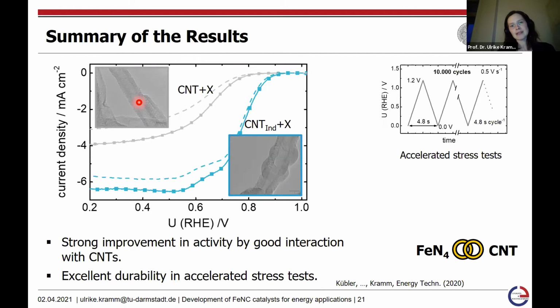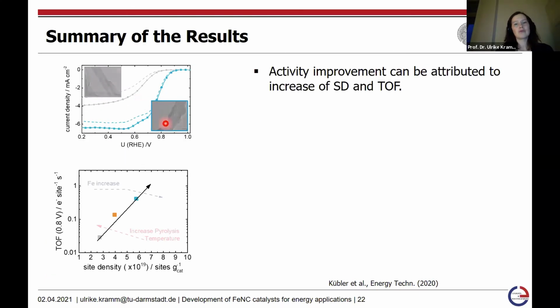When we then analyzed the composition of the catalyst materials in order to identify whether we were able to improve the site density or the turnover frequency, what we were able to show is that, so this is a non-functionalized system, this is for the pyridine functionalization, and this for the indazole functionalization. As you can see, by this functionalization, starting from the non-functionalized system, we are even able to increase the site density and the turnover frequency. And this was quite nice, as typically it's only one of the factors that you are able to improve.